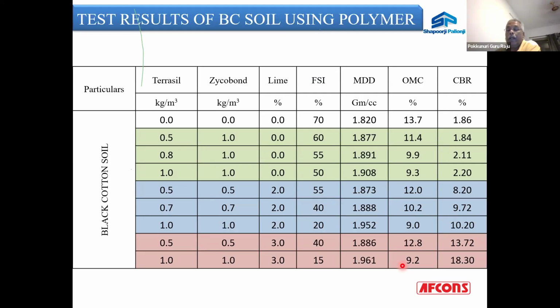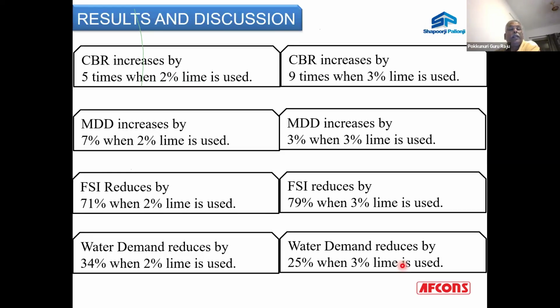So these are some of the interesting conclusions which were drawn during the research time. If you see the results, CBR increases by 5 times when 2% lime is used, but it increases by 9 times when you use 3% lime. So it all depends on your requirement, whether you want to increase your CBR 3 times, or 5 times, or 9 times. Based on your requirement, you can always choose what type of chemical dosing is required, what type of cement is required, what percentage of lime is required, and what doses of chemicals are required.